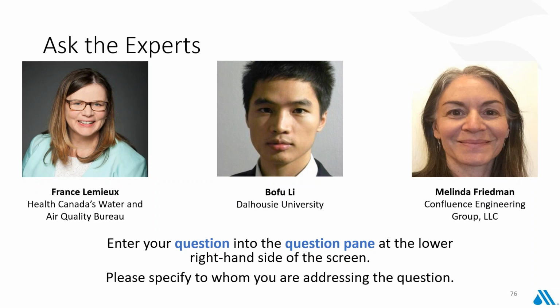Okay, great, thank you. All right, next question. I think this is also for you, Melinda, but other folks feel free to join in. Will the 0.8 milligram per liter chlorine residual actually be capable of forming a lead-4 species? Is lead-4 actually relevant in the system as opposed to the pilot test? Yes, yes. The surface water that was in the pilot rig had a residual of around 0.8, and we did see the lead-4 in the pilot rig at that chlorine residual. And yes, we believe that it is contributing to the extremely low lead levels that we're seeing out in the distribution system. Again, we can't rely on it, and it's not one of the optimal corrosion control treatment strategies in the existing or proposed rule because it can't be relied on since chlorine is so reactive.